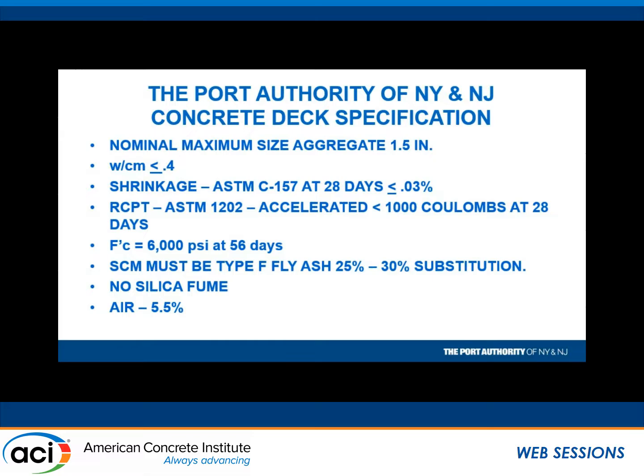So I said to my colleague in the concrete lab, do me a favor. Let's try to measure the shrinkage as soon as you can strip that prism without damaging it. Let's see what we get. He did that, and he stripped it in 10 hours. And we measured initial shrinkage from 10 hours on out.